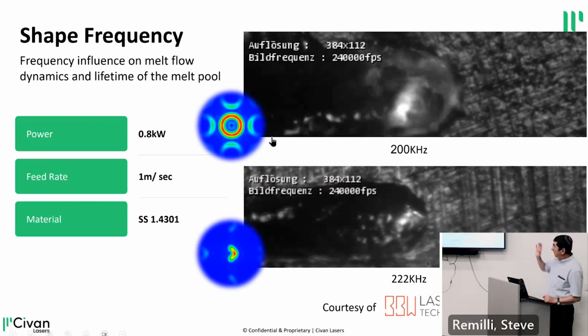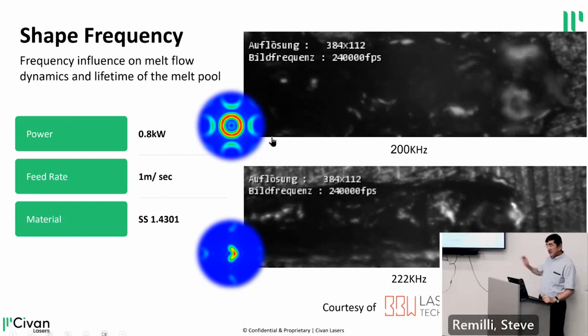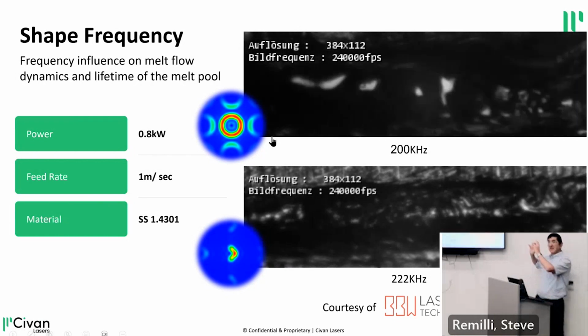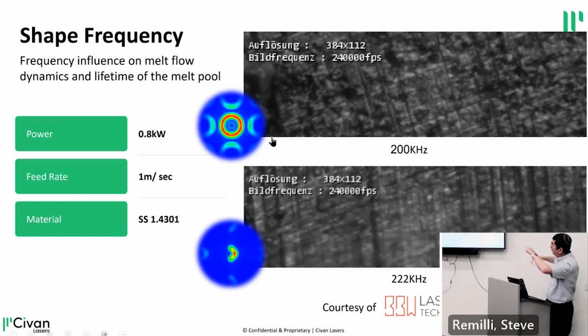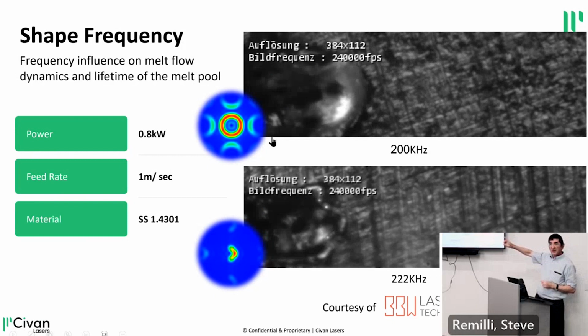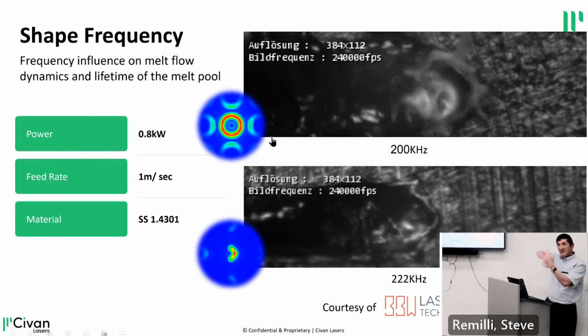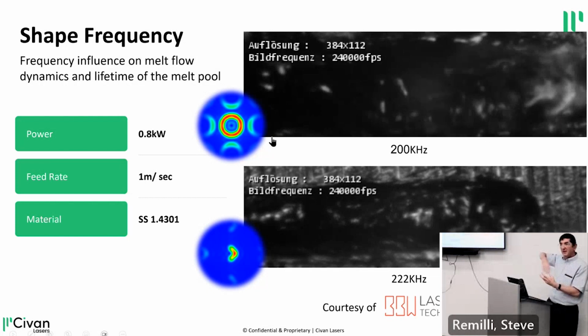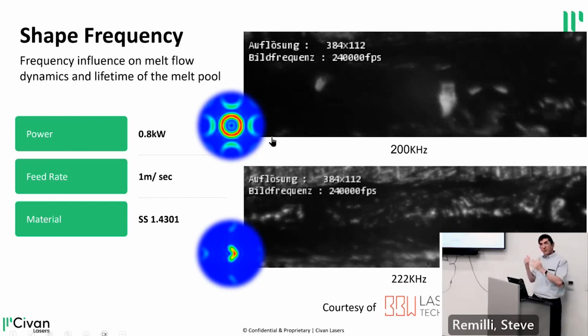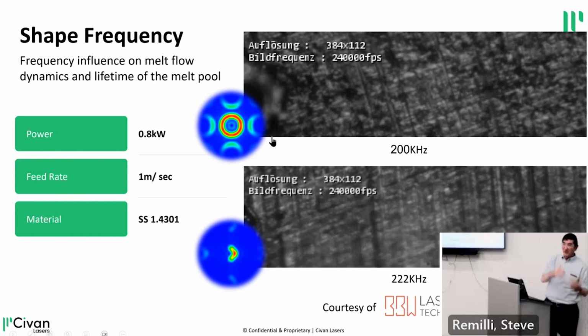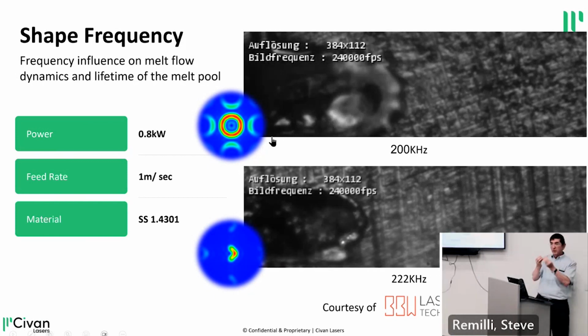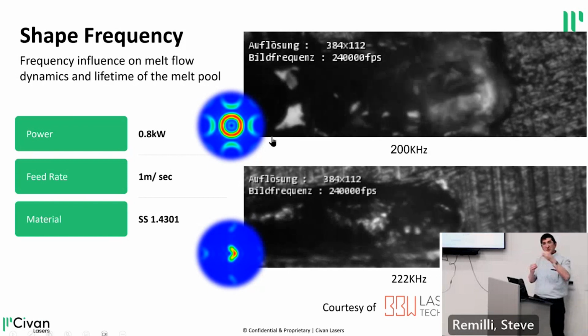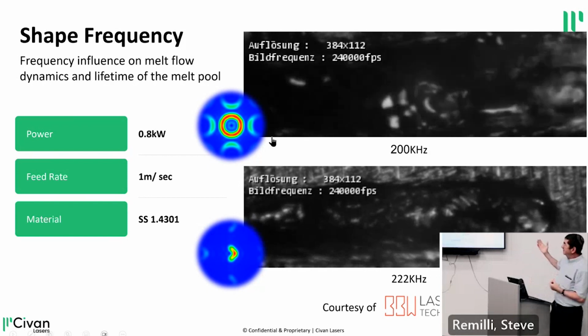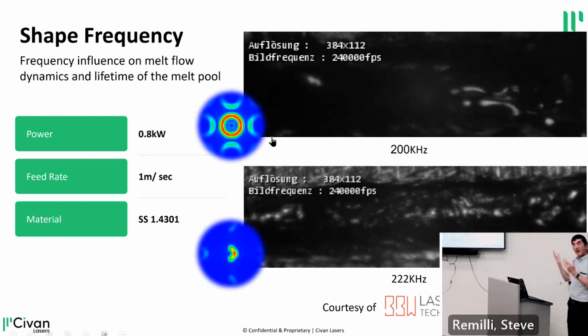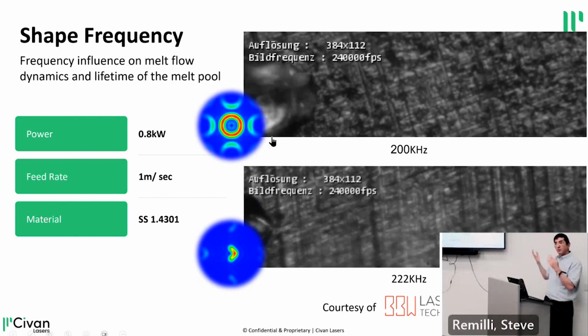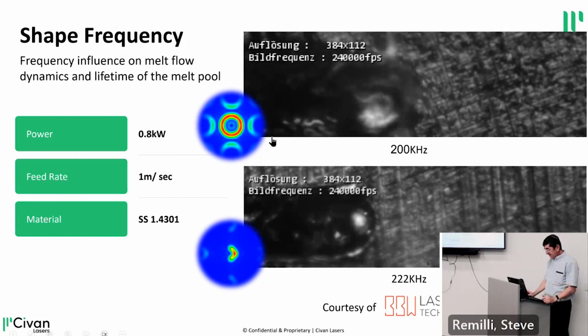And the point here is that we have 2 different shapes. And what you can see is that in the top, the material stays liquid this whole time, whereas at the bottom, it resolidifies very quickly. So that means that by providing kinetic energy to the material and by providing particular currents, you can control the rate of resolidification. And the rate of resolidification is what's going to control the quality and the phase of the metal when it becomes solid again, okay? So this is, again, a powerful tool that there's no other way to do, but now you can really control what's happening in this process of resolidification.